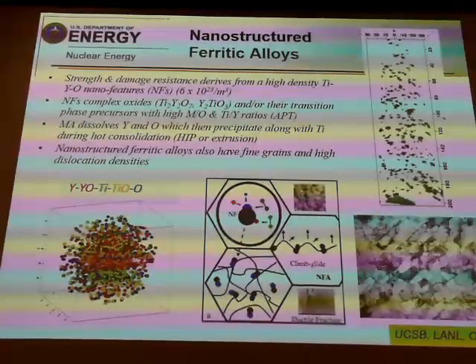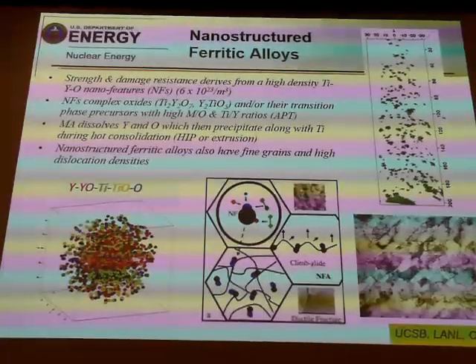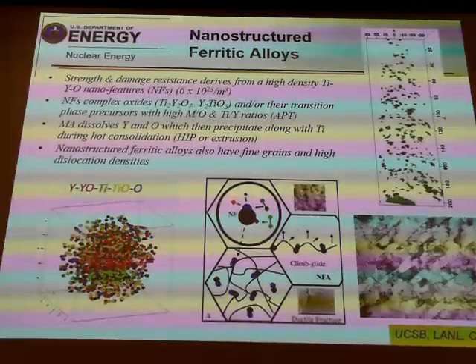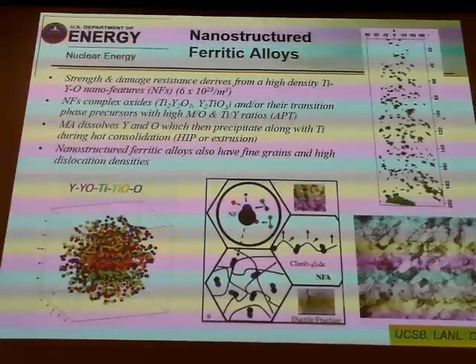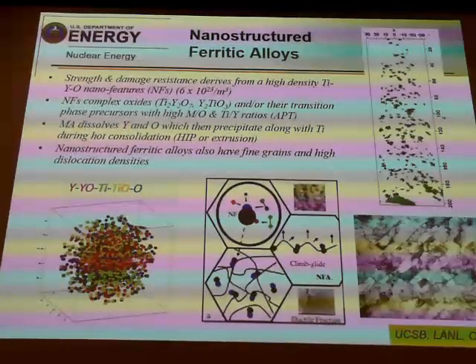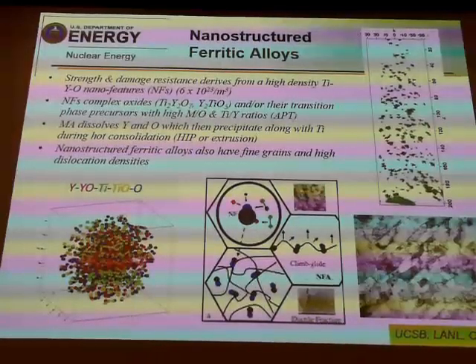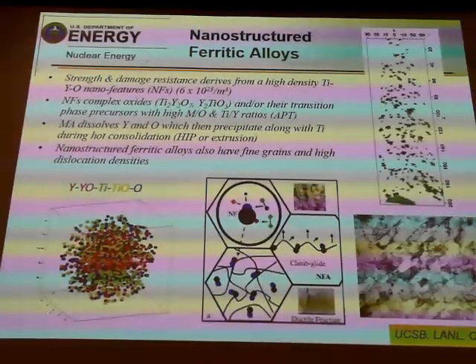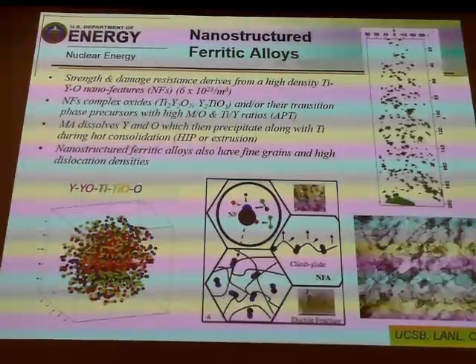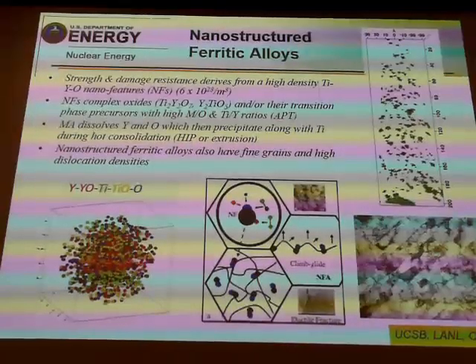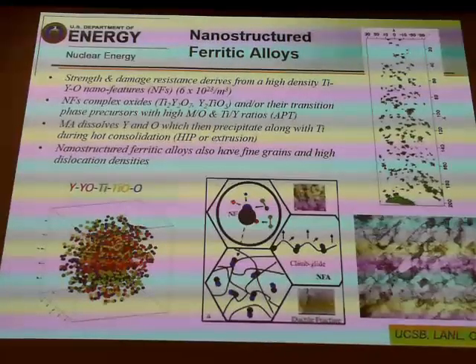These materials are also named nanostructured ferritic alloys. They have a very fine dispersion of yttrium, titanium, yttrium, oxygen nano features with numbers up to 6 times 10^23 per meter cubed. And this is an APT image on the far right side of a heat that we made at Los Alamos in collaboration with Oak Ridge and UC Santa Barbara.